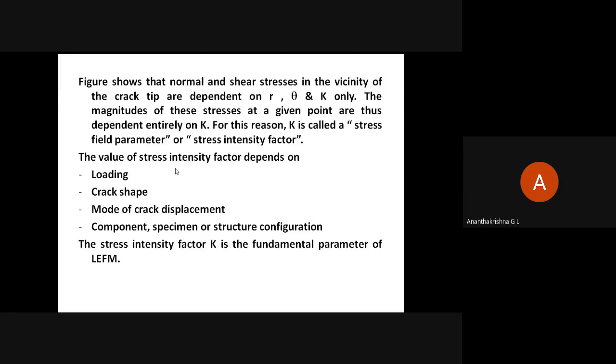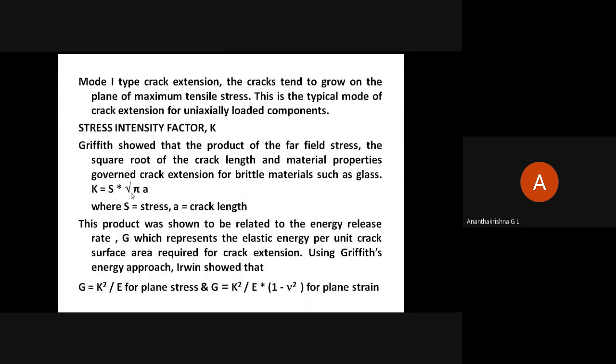Coming back to the stress intensity factor, K is equal to stress into root pi a according to Griffith. Then according to Irwin, the energy release rate G is equal to K squared by E into (1 minus nu squared) for plane strain and K squared by E for plane stress. The other way, stress is equal to K by root pi a. So the stress intensity factor is a very, very important parameter in linear elastic fracture mechanics. Is that okay?